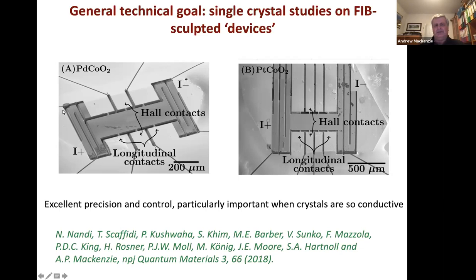And what you're seeing here, in both of these cases, I hope people can see my cursor. You can see the edge of one of Seung-Hoon's crystals. That crystal has then been cut into a particular shape using focused ion beam lithography or sculpting, so that for this one on the right, we can run a current in from the top, and the crystal is highly anisotropic. So we run it through a long meander to allow the current to homogenize through all the planes before we get to the active channel. Then in this particular device, we had 8 voltage contacts on it to allow us to make 4 independent Hall voltage measurements and various different combinations of magnetoresistance measurements. And then we run it out through an equivalent meander on the other side. So this is a really relatively new way of being able to do transport, and it's incredibly useful both in general and in particular on these delafossites.